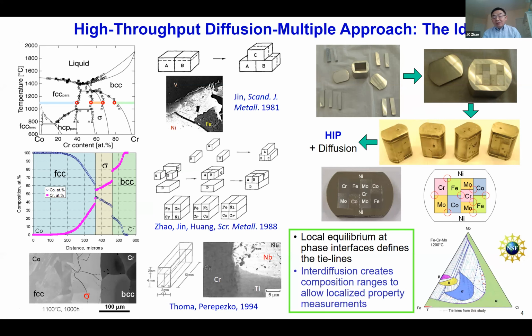And then we take it out and we do a heat treatment, long-term heat treatment to promote all the diffusion so that we can measure diffusion coefficient, we can measure phase diagrams. So each corner of this triple can allow us to measure the entire ternary phase diagram. So this is the example for iron, chromium, molybdenum. Okay, so the very efficient way of getting tie line information, like what Greg Olson was saying the other day about the importance of that as one of the genes of materials. So that's the phase diagram determination part.